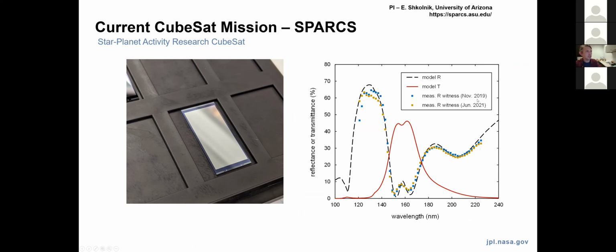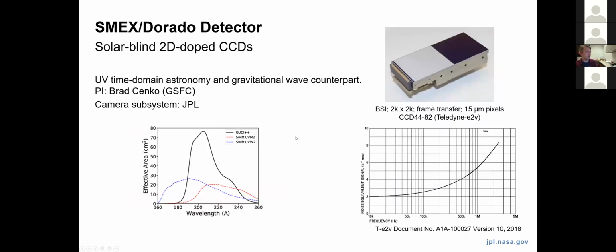This is just meant to show that for these filter structures, we've measured some of them now for more than a year in storage without seeing large changes in the measured reflectivity in this case. So there's reason to believe there's some stability in this multi-layer ALD approach. A couple of weeks ago, you heard from Brad Cenko at Goddard on the Dorado mission. This is also considering the use of these metal dielectric filters, again, for a band here centered closer to 200 nanometers.